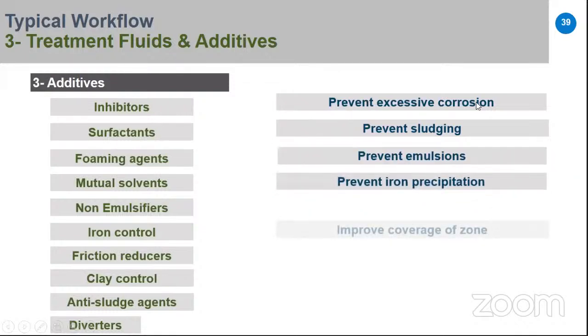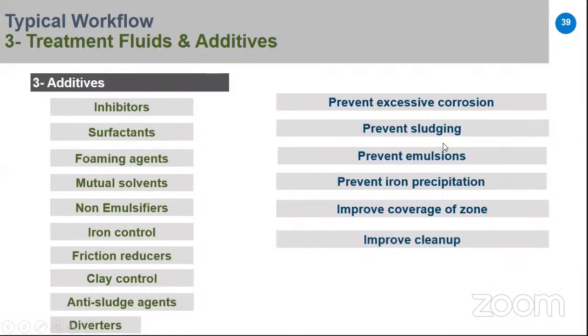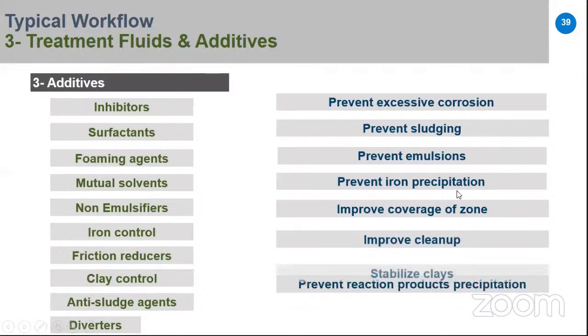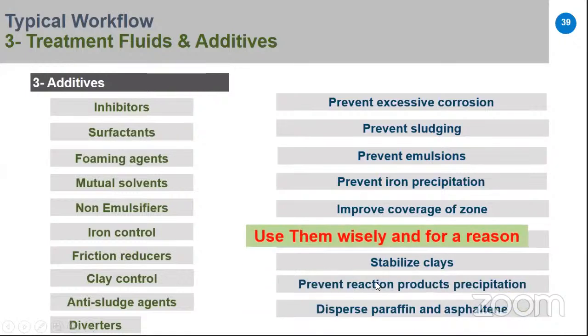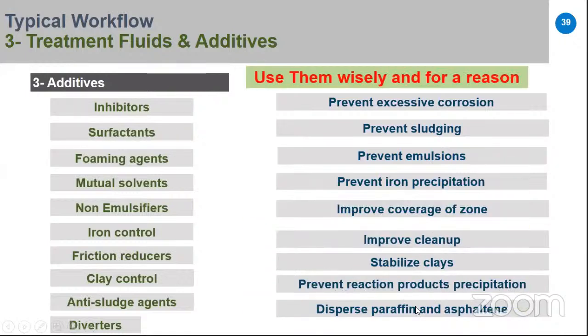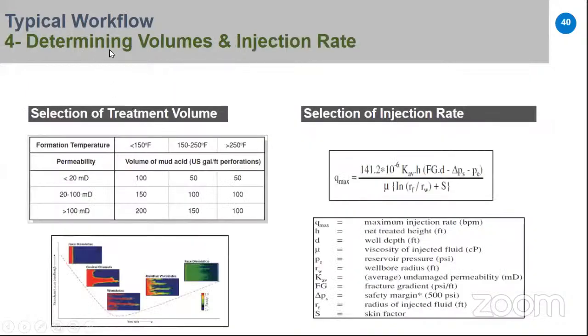So the general functions are to prevent excessive corrosion, prevent sludging, prevent emulsion, prevent iron precipitation, improve the coverage of acid over all zones treated, improve cleanup, stabilize clays, prevent reaction product precipitation, and disperse paraffin and asphaltene if you have them in your oil. The general rule is to use additives wisely and for a reason, not to add any additive without reason because they are costly materials. Then we go to determine the volume of the job and the injection rate.